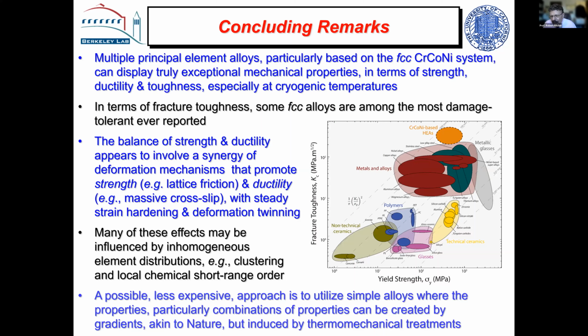In the toughness issue, the microstructure doesn't seem to be so important if you think about it, at least at the micron scale, because everything is just equiaxed grains. So we've looked to a lower level, which is the local ordering. But when it comes to corrosion, I think composition is very much more an issue. And with these BCC materials, when you're looking for very high temperature strength, but you're also looking for low temperature ductility, the refractory alloys have terrible corrosion resistance, as you know, terrible oxidation resistance. And so the choice of alloys, the choice of elements, will be very important.